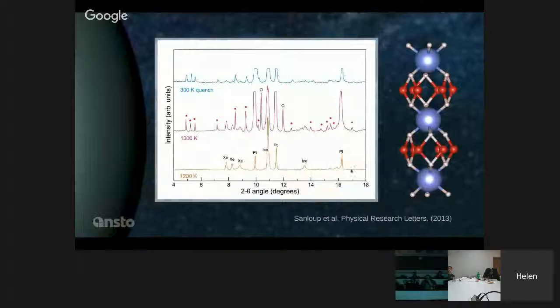So this is the first pattern. We're at 1,200 Kelvin. So we're just warming up. Here is xenon sat here, relatively happy. Here is the platinum peaks. There's another one. And here are the ice peaks. At this pressure, ice is actually a bit of a weird material. It's not hexagonal, so it doesn't form six-fold snowflakes. It's cubic. So it would form fourfold snowflakes.